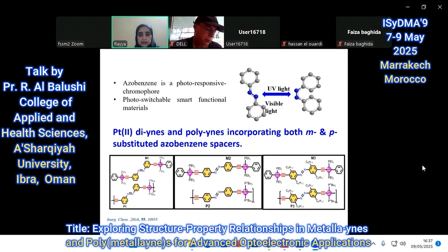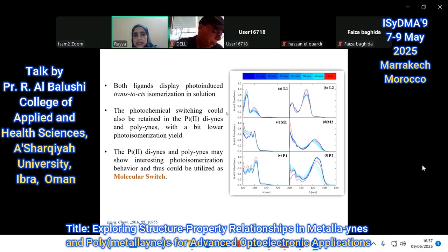This is the polymer with the dimer. This is of course the photoisomerization test, and we found that both ligands, the para and the meta, displayed photo-induced trans-cis isomerization. This photoisomerization is more clear with the ligands than with the dimer and the polymer, and this could be because of these big units, the platinum unit there, which might hinder the switch a little bit.